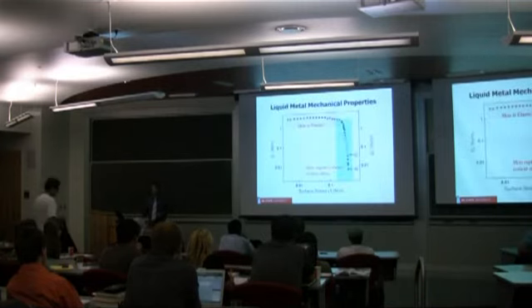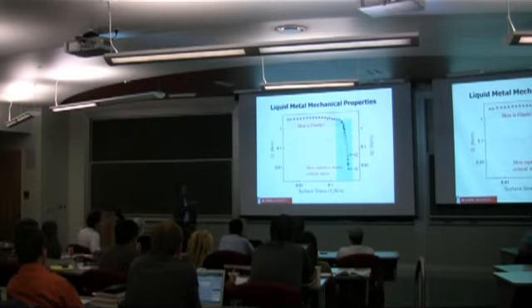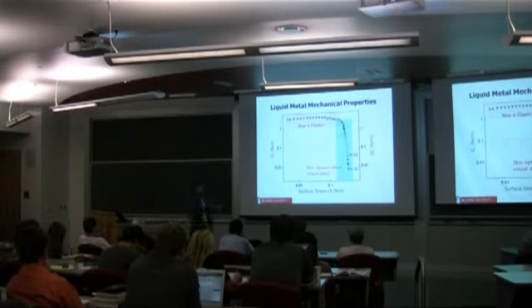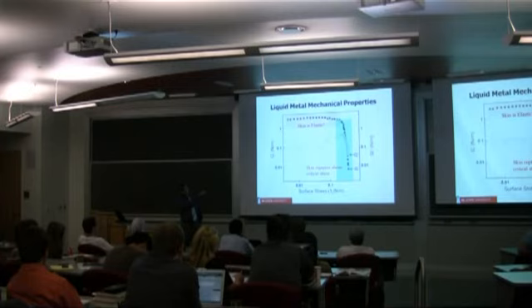So we can capture this or sort of quantify it in this plot. Let me walk you through this because you're probably not used to seeing plots of this nature. So this is G prime. This is what's called the elastic modulus. If you think back to freshman physics, this is very much like Hooke's constant. It tells you sort of how hard it is to stretch a spring. And this axis is surface stress. So this is kind of how hard you're pushing on that skin. And what we see is that at low stress, the skin is elastic. So you can think about this again like Hooke's constant.